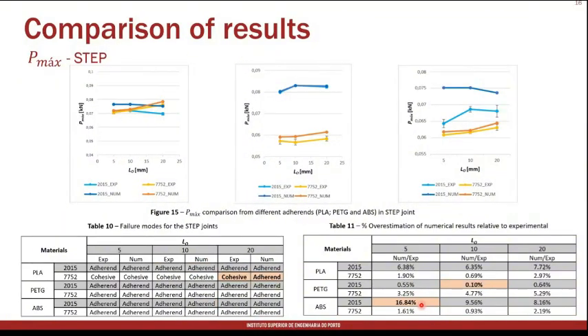In the step joint, we noticed that for our single step geometry, we fragilize the overlap region because we have a sort of cross section because of the step, and we had almost always an adherent failure starting from the shortest overlap. So we have very small difference in maximum load as a function of the overlap length, but we have a maximum overestimation for an ABS 2015 joint of almost 17%.